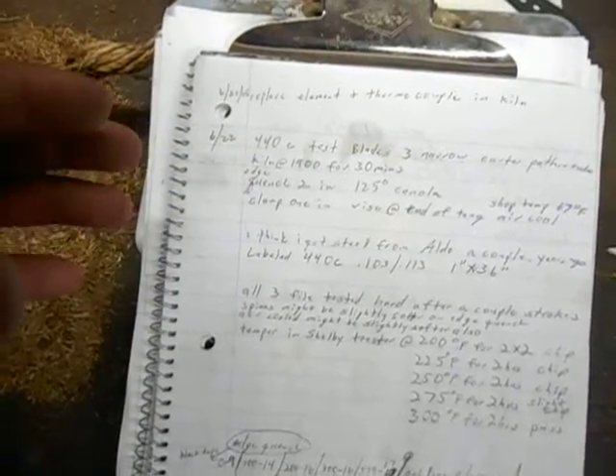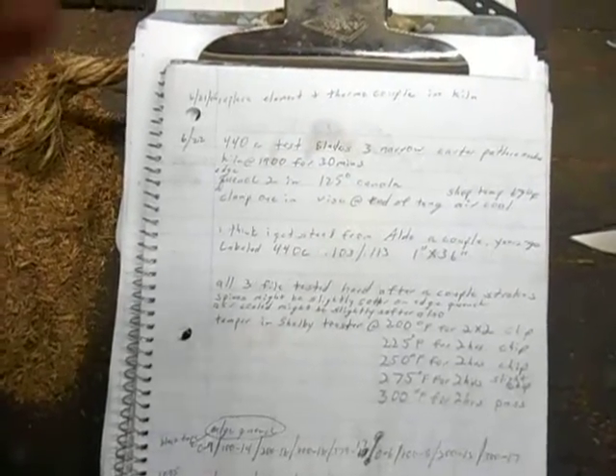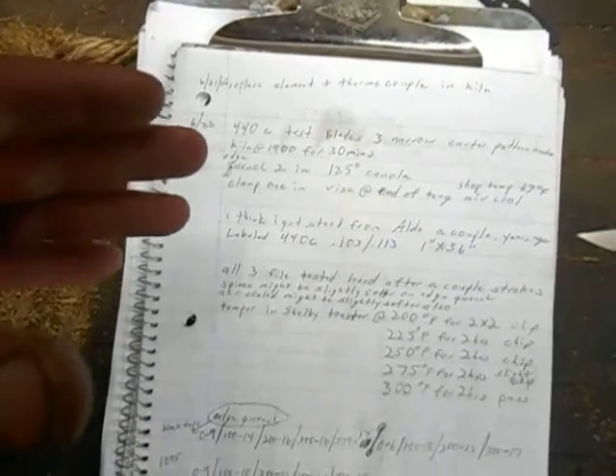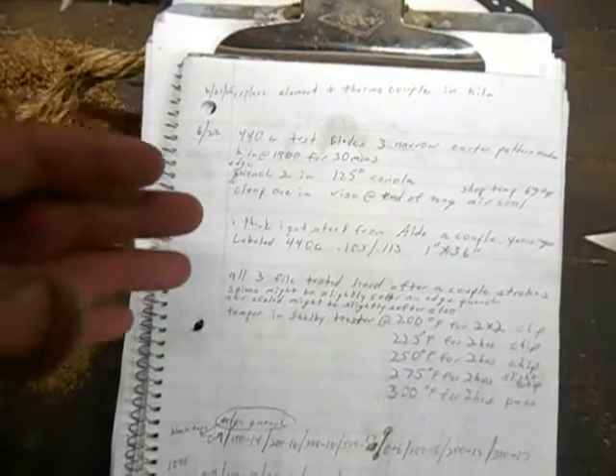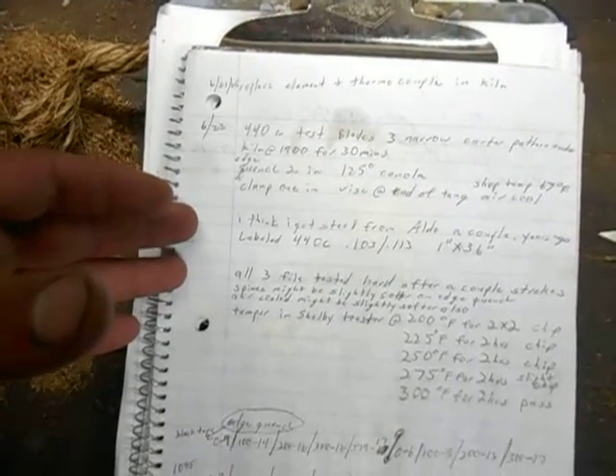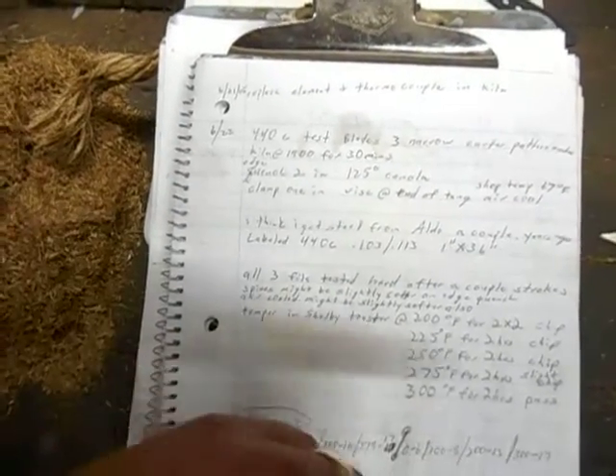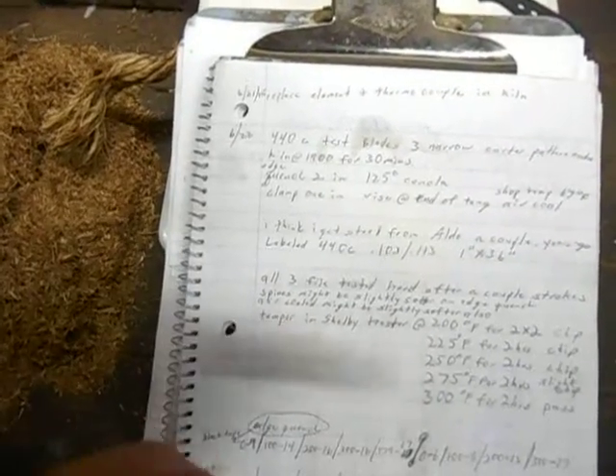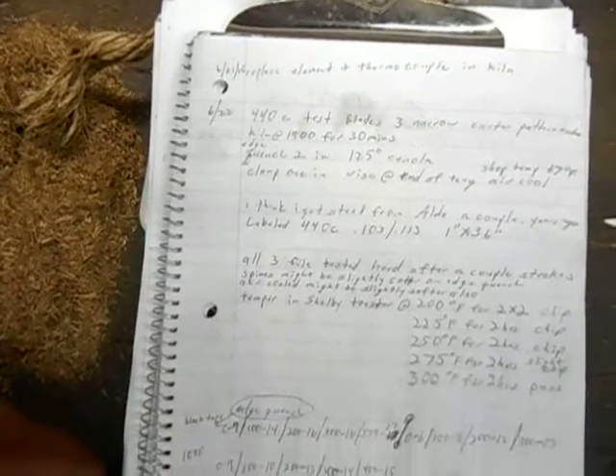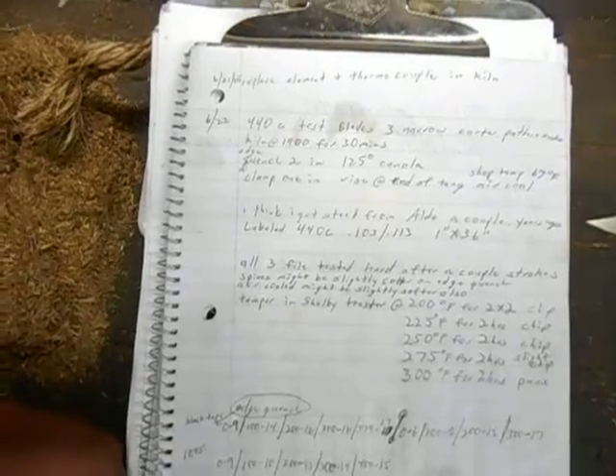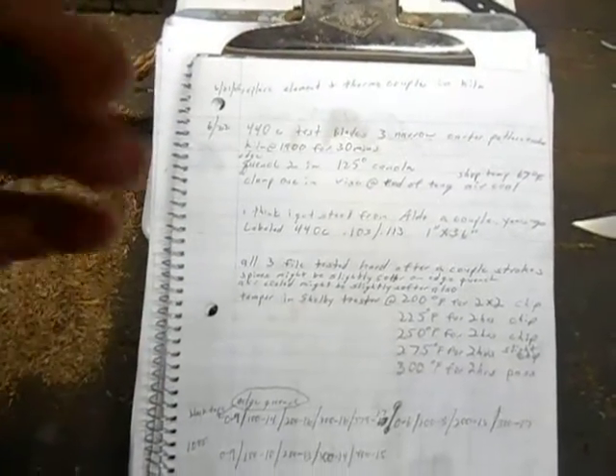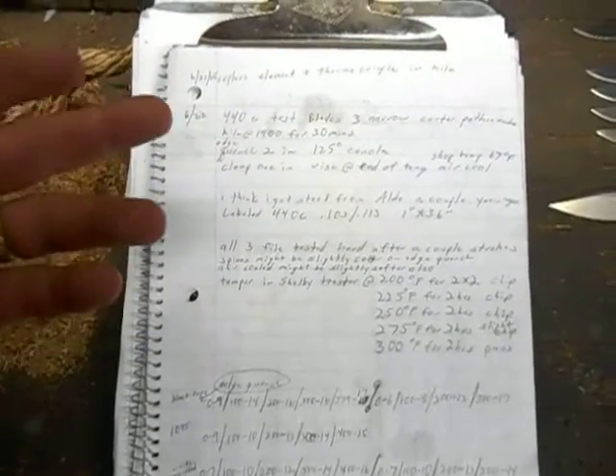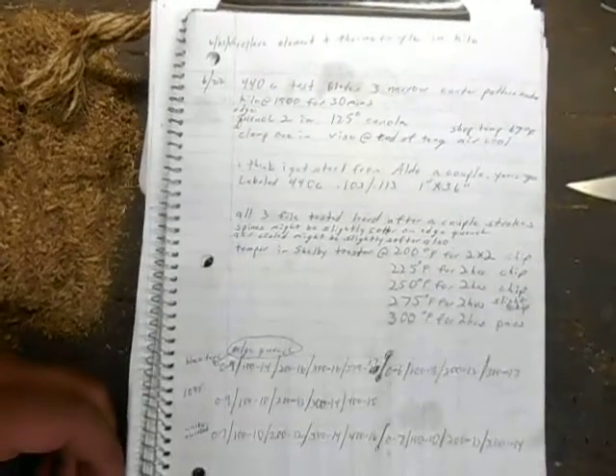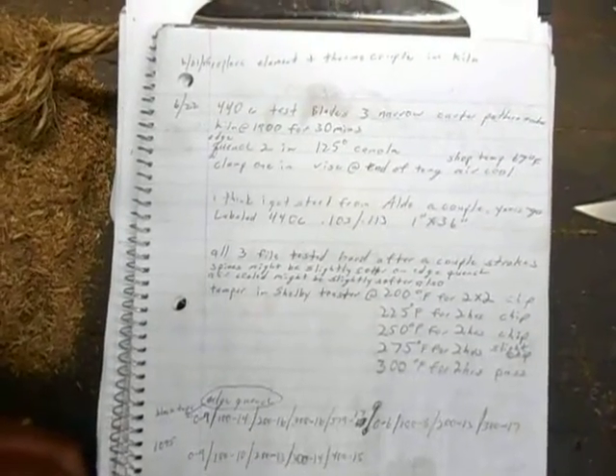Then I got to chatting with some folks, and they were telling me that with stainless steel it needs to be fully hardened to retain the stainless qualities of the steel. So we'll find out about that when I break these edge quench blades. After I test them and learn everything I can about how they perform, then I'll go ahead and take the pieces and put them in a pan of water and see if that holds true or not.